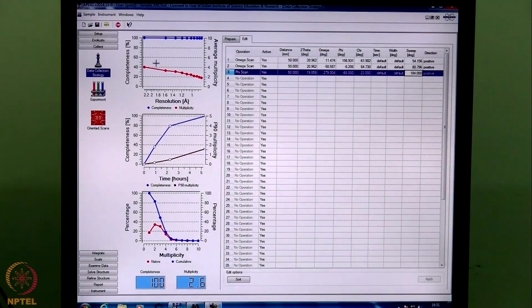The plots here on the left hand side indicate that the percentage completeness, shown in blue, is 100% with respect to resolution. So the completeness is going to be 100% for all the resolutions that we want. The average multiplicity for high resolution is going below, but it is very high at low angle. Similarly, the completeness versus time is plotted here, and also the percentage versus multiplicity is plotted here.